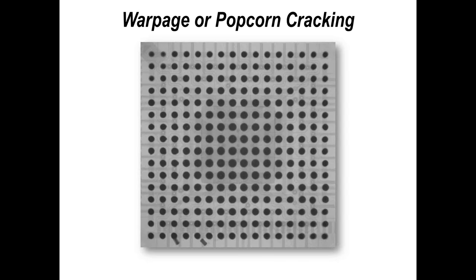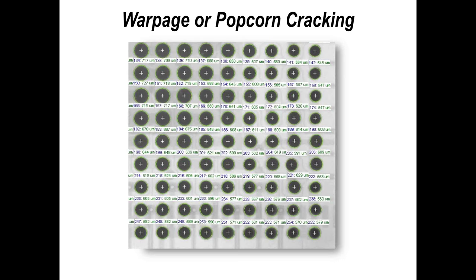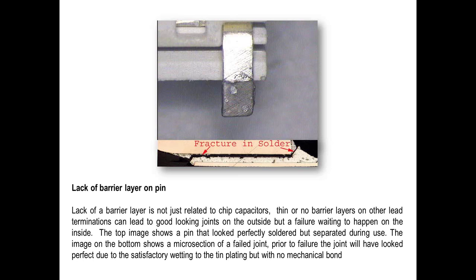If you look around the outside of the package, you can see the balls are a certain size. If you start to go into the center of the package, you can see the balls are slightly larger. And if you then were to measure that, you can actually see a trend. So what I'm showing you now is something that most X-ray machines will allow you to do, measure ball size. And it's a great process control tool to see if there's any warpage on the packages. You can measure the corner heights, you can measure the center lines and corner heights using laser. But this is a nice technique to identify if you've got a problem with parts, or potentially a problem with parts with some degree of warpage.